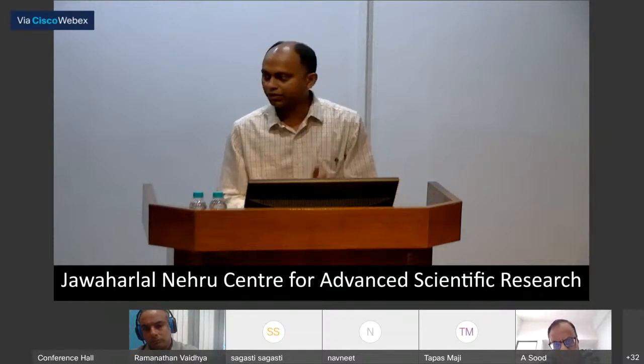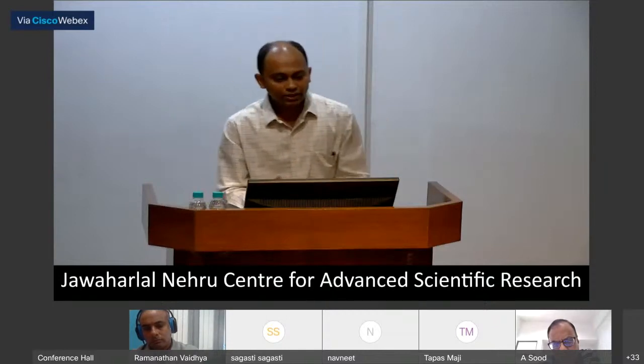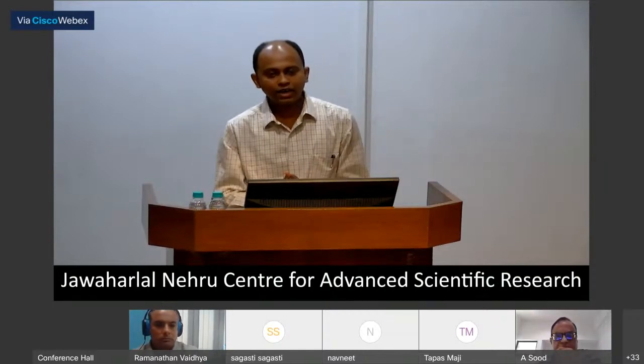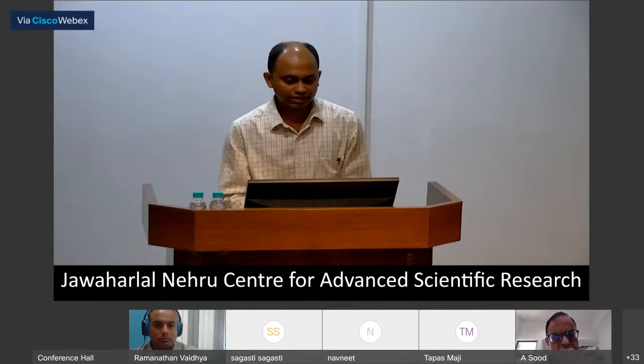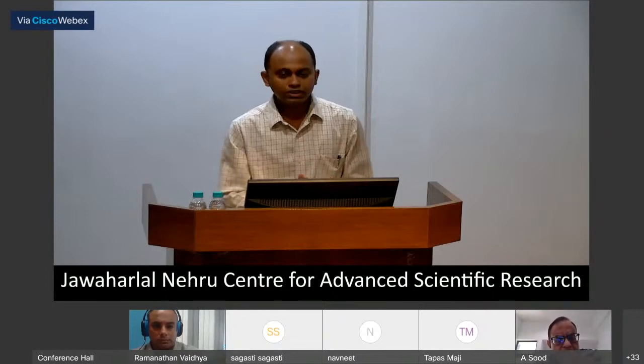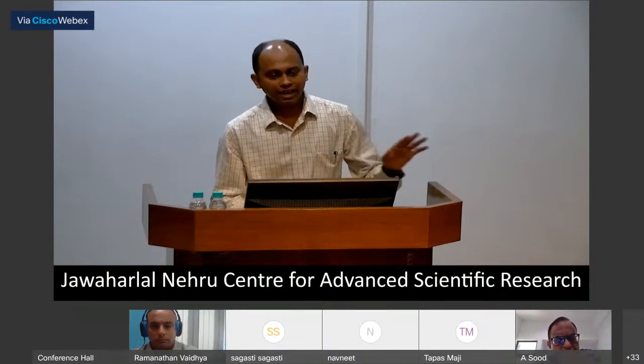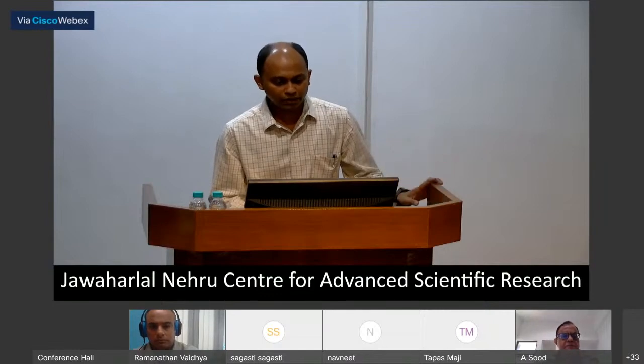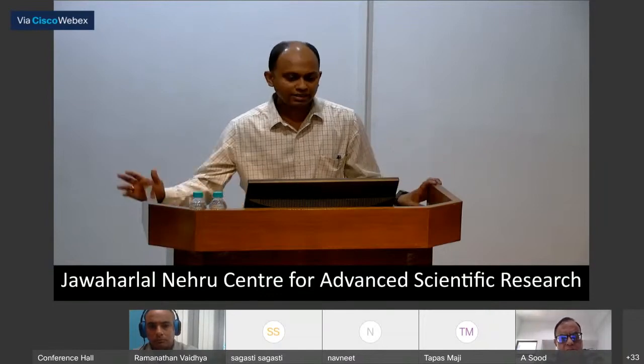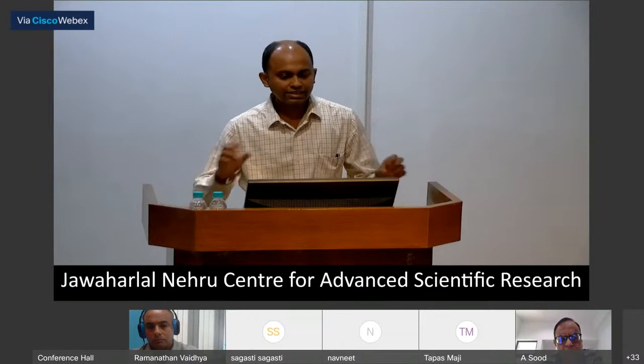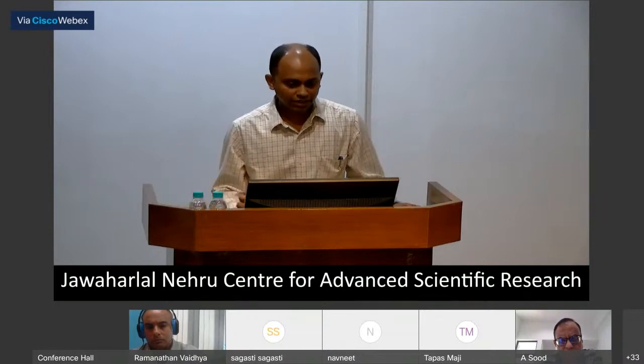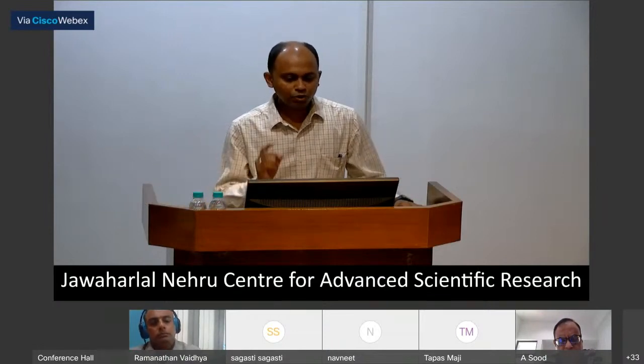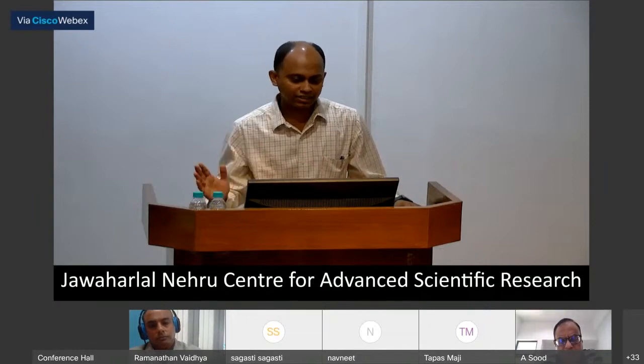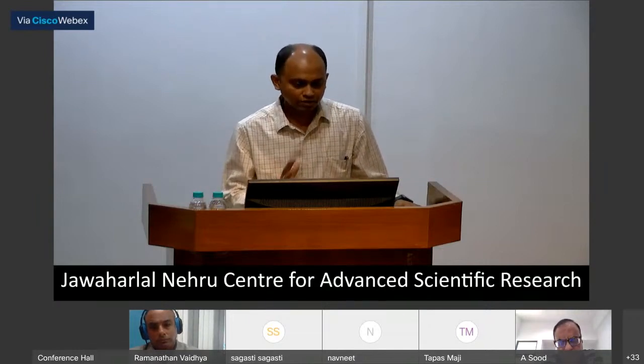So now, why is it ordering? Because this silver antimony telluride has a rock salt structure, and in the rock salt structure the cation positions sit in the octahedral position. The size of silver plus is 115 picometer, whereas antimony plus 3 is 79 picometer. So there is a size mismatch as well as a charge mismatch. Now cadmium 2 plus has a size exactly the average of silver plus and antimony 3 plus. So that's why it creates the ordering. That is the chemical intuition we have.